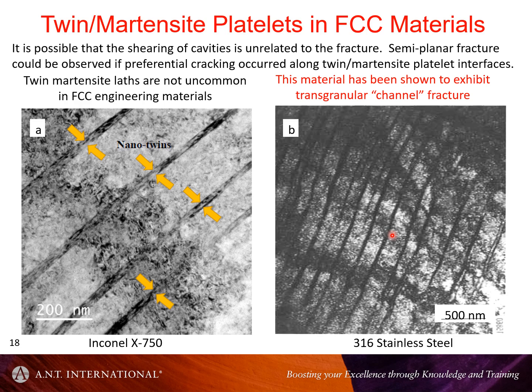So if you see one example in an unirradiated case, I think it's fairly highly likely that you're going to come across this kind of thing at some point in one of your irradiated samples. And judging by the work from Puyan, it looks like that's sampling a weak point, and you're going to see fracture where you have those platelets.